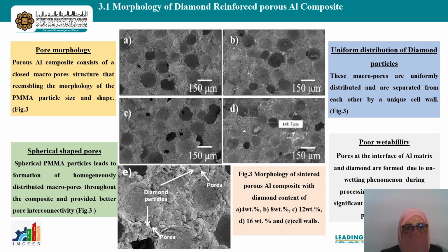For the morphological analysis, if you can see the pore structure, it has a macropore structure that resembles the morphology of the PMMA particle size and shape. Also, there was a uniform distribution of the diamond particles, as evident from 3E. But there was poor wettability between the aluminium and diamond particles, as evident from the pores available at the interface of diamond particles and aluminium. And there are spherical porosities, which help in the homogeneous distribution of macropores throughout the composite and provide better pore interconnectivity.